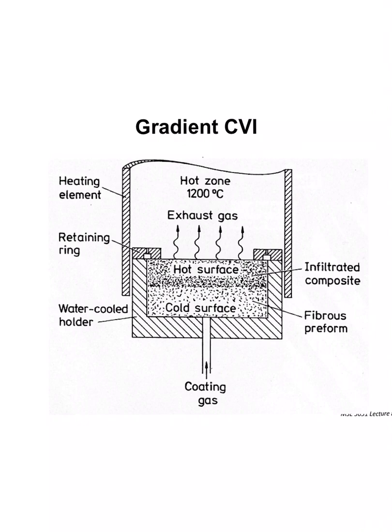You do the same thing in that you have your reticulated carbon skeleton in here, and you bring in the same precursor, and what's happening now is that rather than the whole thing being in the furnace, you've got this moving bottom, basically. All right, and so what happens is, as you heat the furnace up, this is at the low position, and you bring the gas in, and that gas stays cool until it hits that hot surface, and then it deposits tantalum again. All right, and you let that go for a little while, and then you inch this thing up by a couple of millimeters, and then the tantalum starts decomposing at the next hot surface, which is now moved into the skeleton. And you just keep repeating this over and over again until the entire thing has uniform tantalum deposition on it. All right, so a very cool process. I hope they paid somebody well, whoever did this.